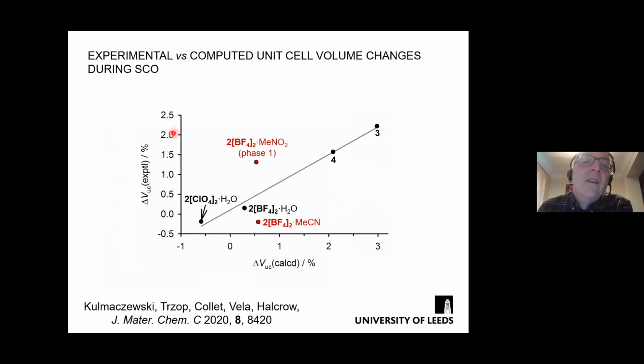However, you look at the calculated structures now. So this is the volume of the unit cell and how the unit cell volume changes during spin crossover in the DFT calculated crystals. And now 4 of the compounds give good agreements, but 2 of them don't. This one doesn't, but this is the crystal which exhibits the phase change during the process. And those phase changes weren't calculated by the DFT. So it's not surprising that this one doesn't work.